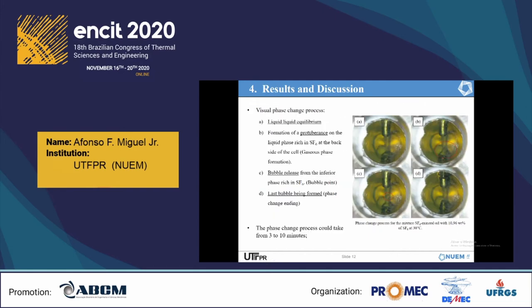The main goal of this research was to identify the phase transitions. All the points obtained throughout the experiments were ELLV points — that means, visually, the phase transitions would start with a liquid-liquid equilibrium. As the pressure drops, it was possible to see the formation of a protuberance on the liquid phase rich in SF6 at the back side of the cell. Later on, a bubble release could be noticed from this protuberance of the interior phase rich in SF6, which would indicate the bubble point of the mixture. On the last picture, you can see the last bubble being formed, indicating the phase change ending.